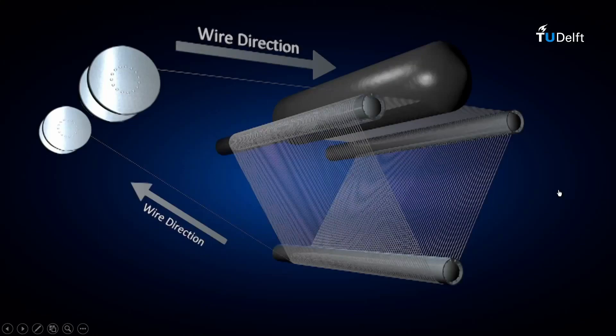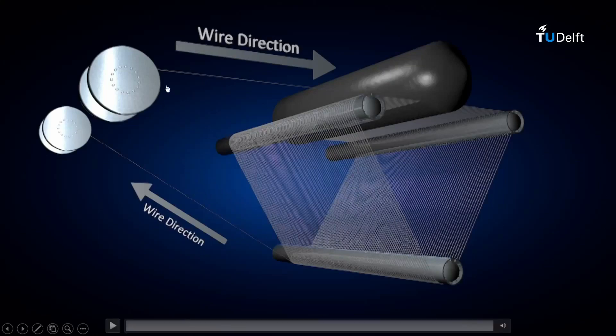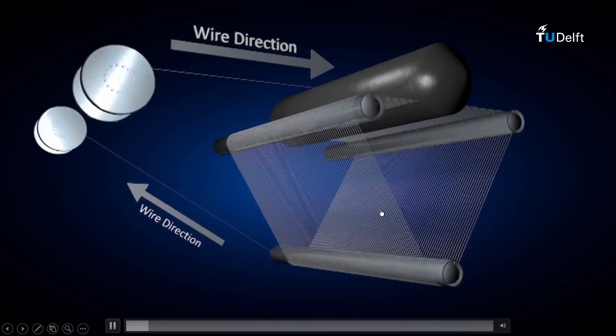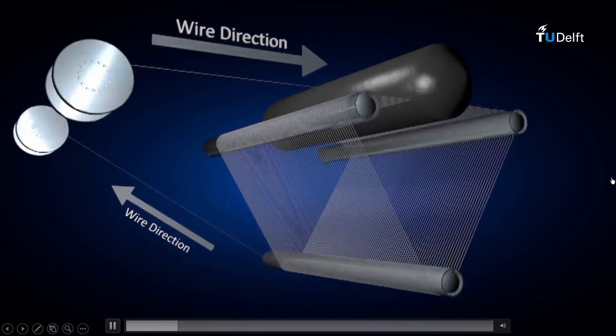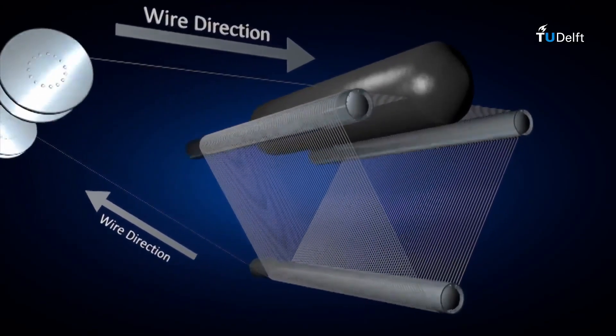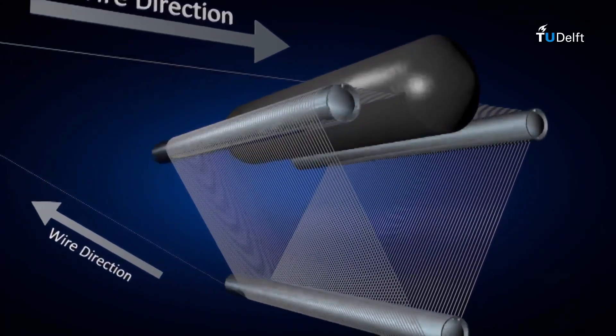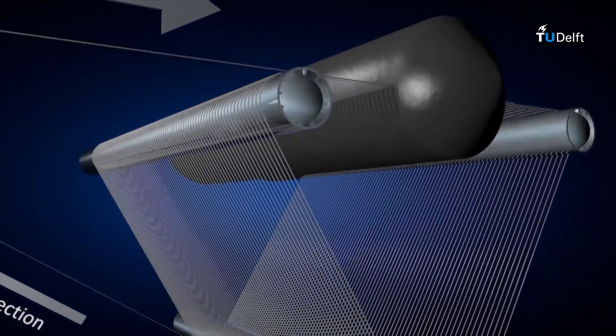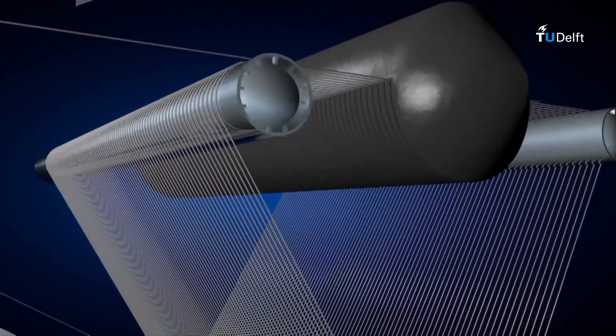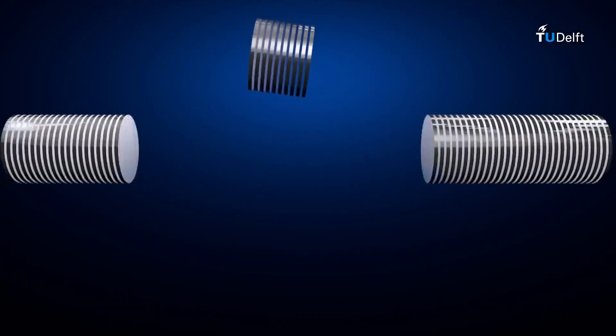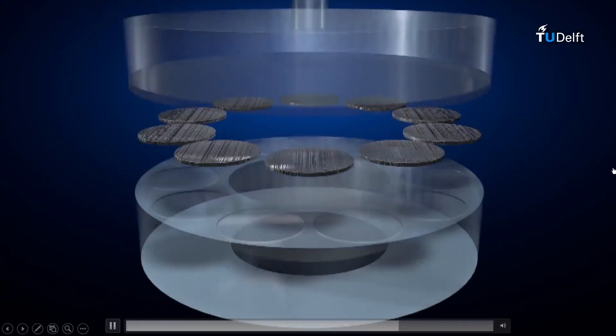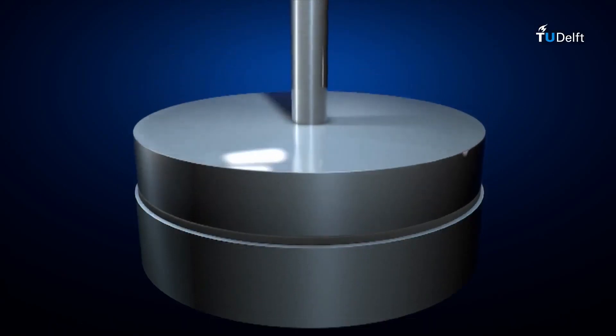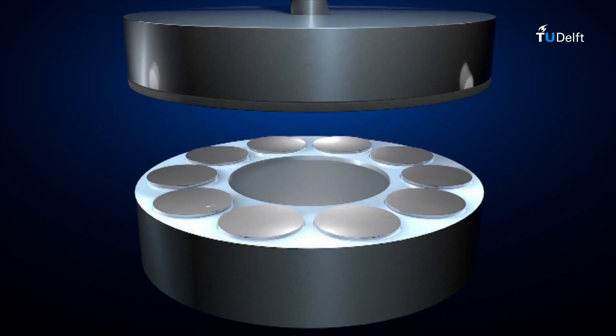The wire cuts from the top and bottom to slice the ingot. The disadvantage of the sawing step is that we waste a significant fraction of silicon as kerf loss. The kerf loss is usually determined by the thickness of the wire or saw, and is in the order of 100 microns of silicon — a large fraction if we consider that typical crystalline silicon wafers for solar cells are 150 to 200 microns thick. Sawing damages the surface of the wafers, so this step is followed by a polishing step.